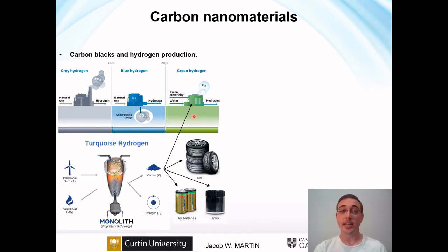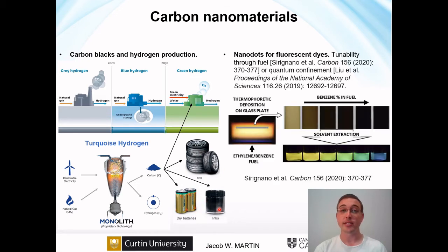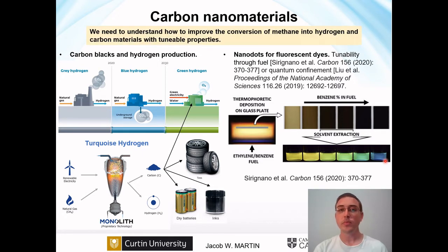There's an intermediate step called turquoise hydrogen, where you use renewable energy to crack the natural gas into a solid carbon and hydrogen. And this solid carbon is carbon black and can be used in tires, in batteries, in inks, and many other things. There's also been some very interesting nanomaterials. So nanodots have been recently synthesized in flames. By changing the fuel, different colored nanodots can be produced. And also by changing the size, they can be tuned as well. So we'd like to understand how to improve the conversion of methane into hydrogen and also how we can tune the properties of these carbon nanoparticles that are coming out.